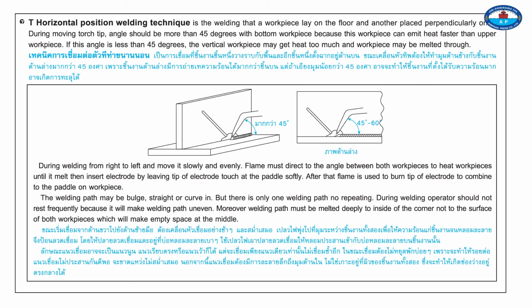The flame must be directed to the angle between both workpieces to heat them until they melt, then insert the electrode by letting the tip of the electrode touch the puddle softly. After that, the flame is used to burn the tip of the electrode to combine with the puddle of the workpiece. The welding path may be bulging, straight, or curved in, but there is only one welding path, no repeating. During welding, the operator should not rest frequently because it will make the welding path uneven. Moreover, the welding path must be melted deeply into the inside of the corner, not just the surface of both workpieces, which will make an empty space in the middle.